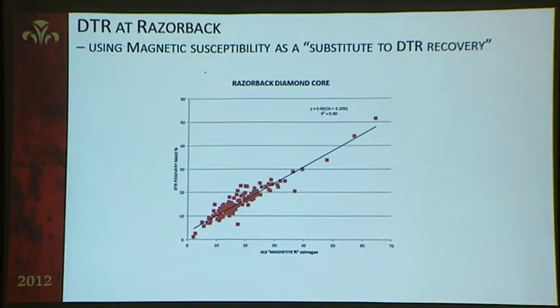Preliminary work on DTR versus MagSUS has shown that the use of magnetic susceptibility measurements made both at the laboratory and downhole may be a useful substitute to DTR recovery. This should hopefully go a long way to reduce the costs and give us a better picture of the distribution of magnetite recovery over our deposits. We've found that there is a fairly robust correlation between DTR recoveries and MagSUS grade, and potentially, given a calibration factor, we may be able to use MagSUS to effectively map the distribution of magnetite.